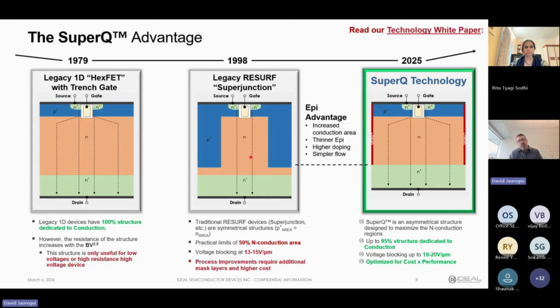this structure. To where now the thickness here, the amount of epitaxial you need to block, now grows at a near linear rate, or the on resistance grows at a near linear rate with the blocking voltage. And so therefore, if you have 100 volts and you go to 200 volts, you're really only increasing the on resistance by 2x in theory. It's a little bit higher than that, but more importantly, a parameter that we look at as a way to gauge the effectiveness of the structure is the volts per micron that you're dropping, meaning how thick is this epitaxial in terms of micrometers, and how much voltage you're dropping across that when you're reverse biased.